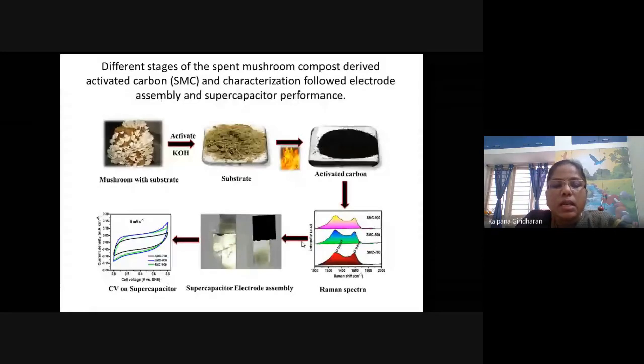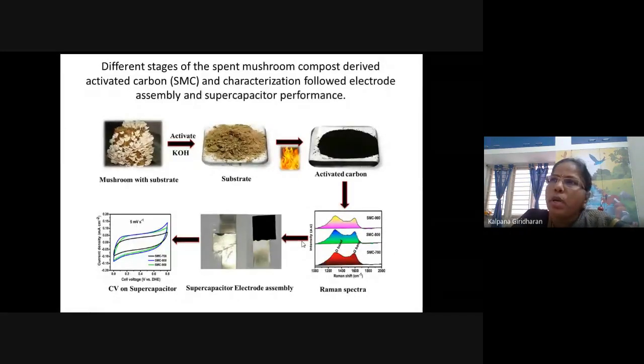After that, as usual, we did the activation procedure. We obtained a very good activated carbon of around 800 meter square per gram surface area.